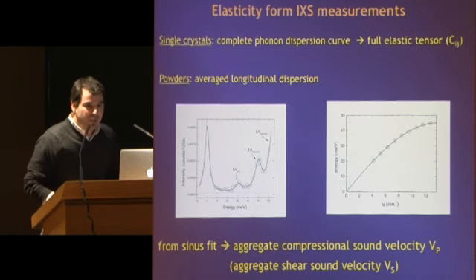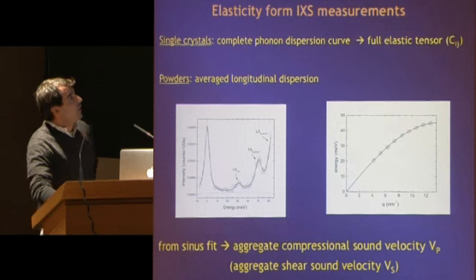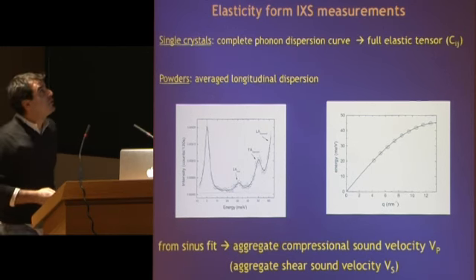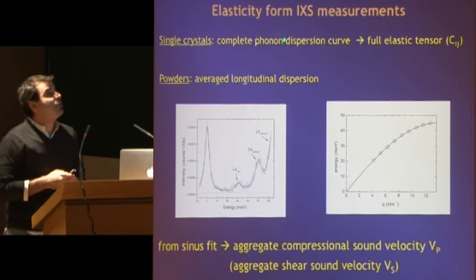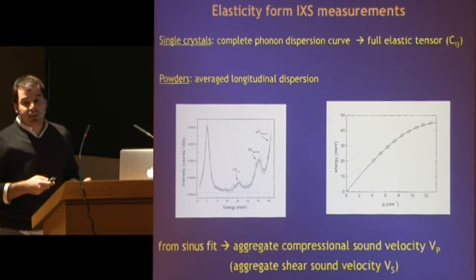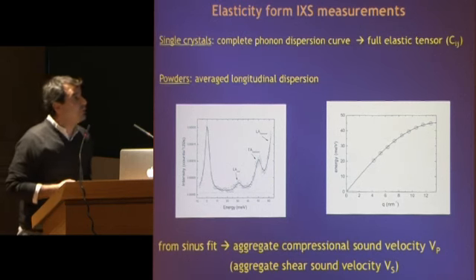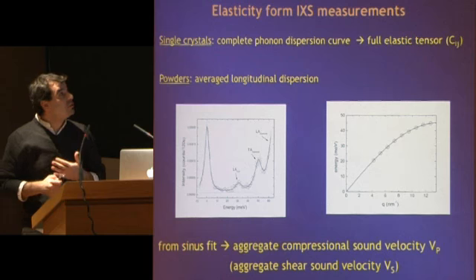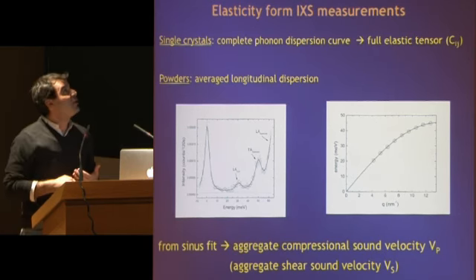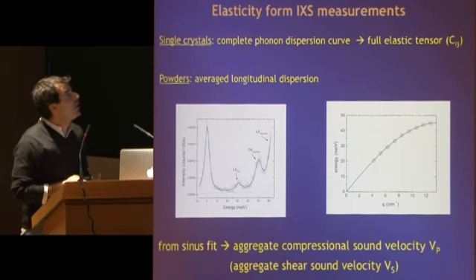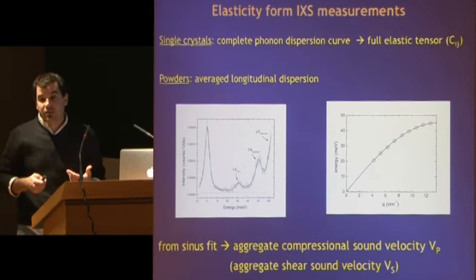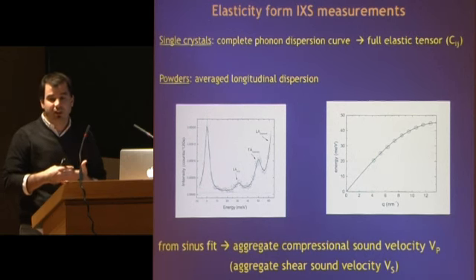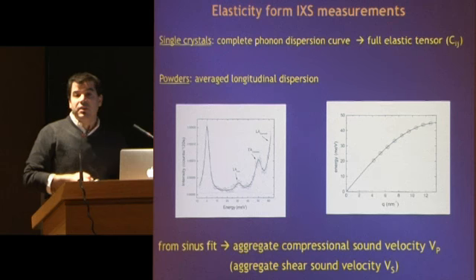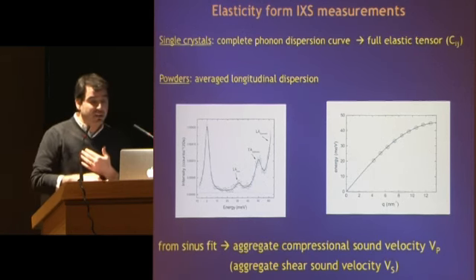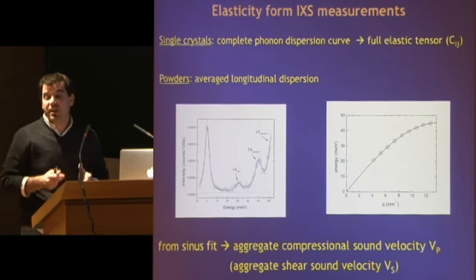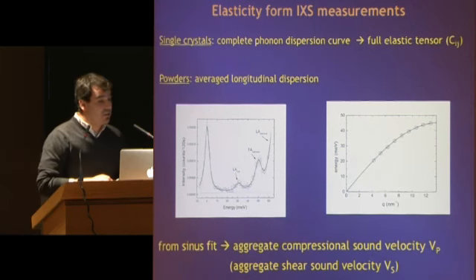So if we just want to limit to the case of elasticity, the richest source of information comes from single crystals, where the complete phonon dispersion curve can be determined, and the full elastic tensor without any approximation or a priori model. However, for what concerns the following of this presentation, and typically experimental megabar pressure, experiments are limited to the case of powders. This is because it's more complicated to preserve a single crystal at such elevated pressure, and in the specific case of iron, the BCC to HCP transition that iron undergoes around 13 GPa prevents keeping a single crystal phase even starting from single crystal BCC.